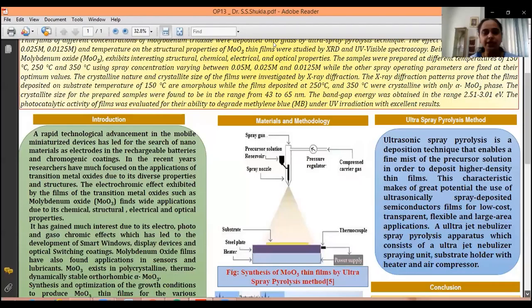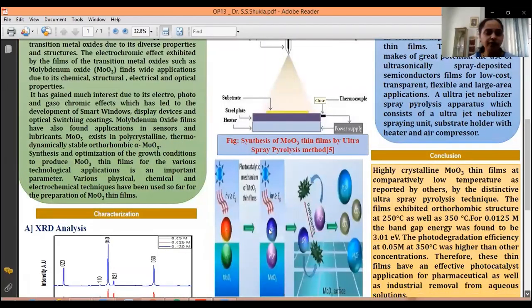The precursor used is ammonium molybdate tetrahydrate, and 0.05, 0.025 and 0.0125 molar solutions were prepared, and thin films obtained at temperatures of 250 degrees centigrade and 350 degrees centigrade were studied. The structural changes and identification of phases were studied with the help of the XRD technique.